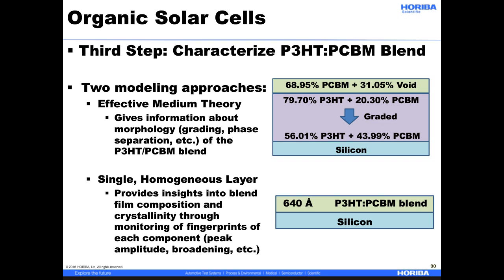So for the effective medium approximation, or the effective medium theory, we end up with some percentages of P3HT and PCBM. This is a graded layer. The P3HT, there's more of it at the top of the layer and less as you go down, so there's some gradient there. In the single layer, you just assume there's no gradient, that it's just a mixture.